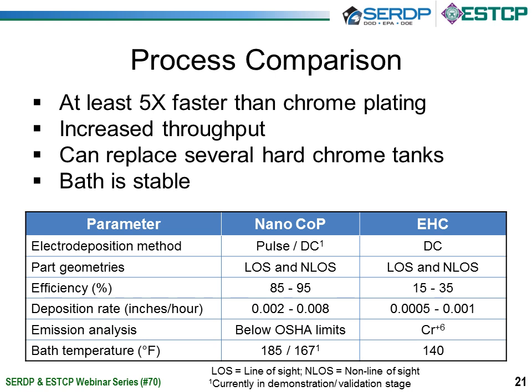So going through the parameters, the nano cobalt phos plates, traditionally it was with pulse plating. We're looking into DC plating, compared to DC plating with electrolytic hard chrome. It can plate line of sight and non-line of sight surfaces. It has a very high efficiency, so this is the conversion of the electrical current that you put into the process versus how much of that goes to producing or reducing the metal versus producing hydrogen. So it's much higher than chrome, resulting in a faster deposition rate compared to chrome.